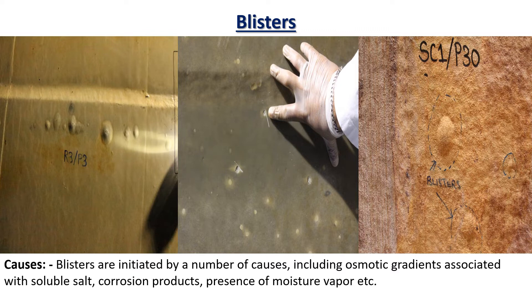These driving forces are: contamination of the steel substrate by water-soluble salts, water-soluble solvents trapped within the applied coating film, and thermal gradients across the coated surface. Even though many blistering problems are commonly associated with coatings in immersion service and high continuous moisture exposures, blisters can and do form by other mechanisms.